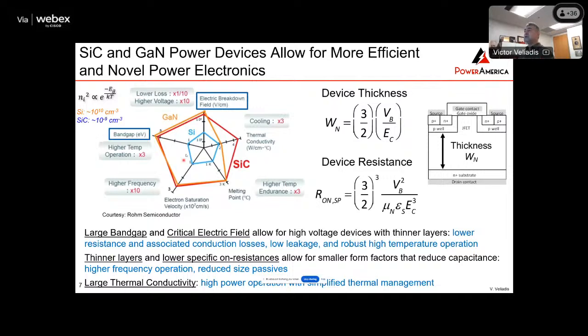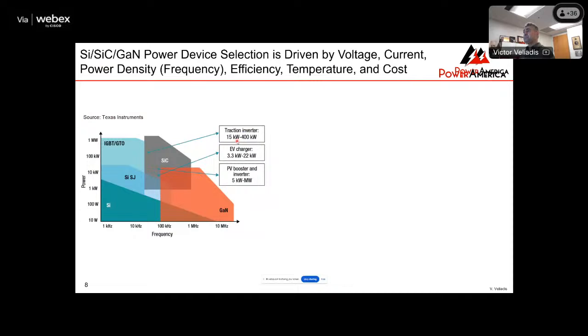And of course, if you look at the high thermal conductivity of silicon carbide, which is shown here, it's more than twice that of silicon and gallium nitride. The large thermal conductivity means you can dissipate heat more efficiently, so therefore your thermal management becomes simplified. So this is the reason why a lot of work and effort has gone over the last 3 decades into silicon carbide as well as GaN for power devices.